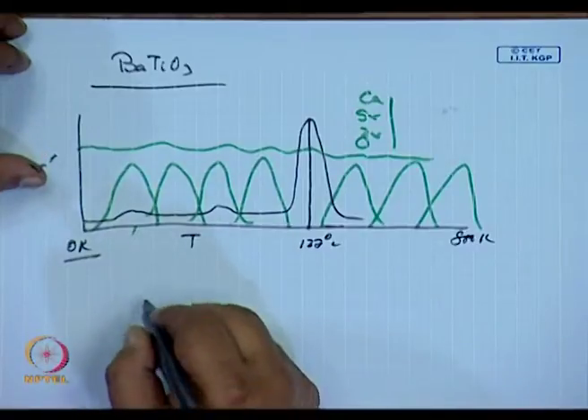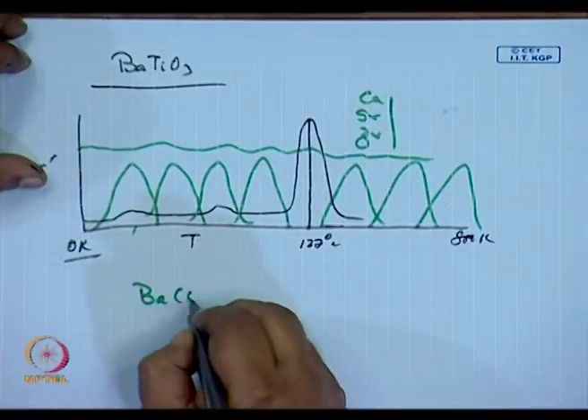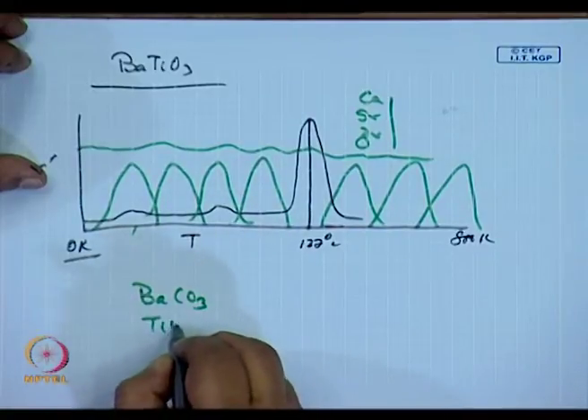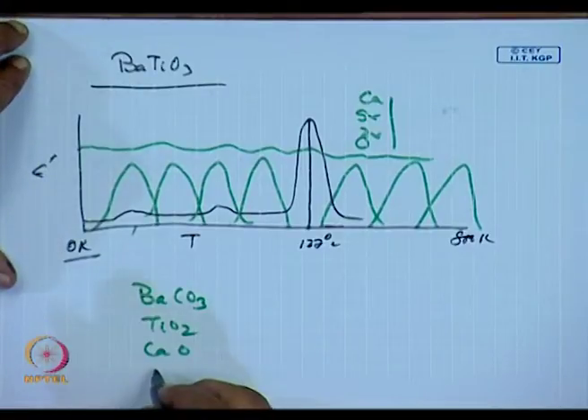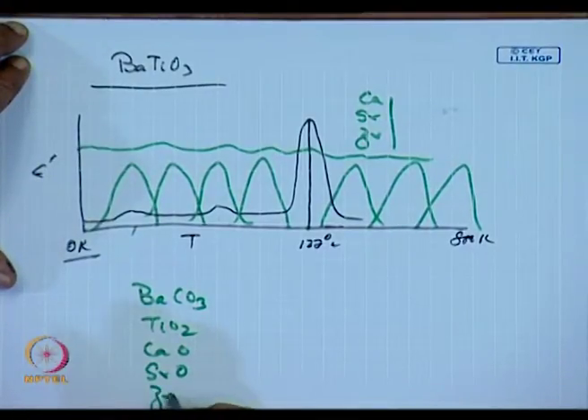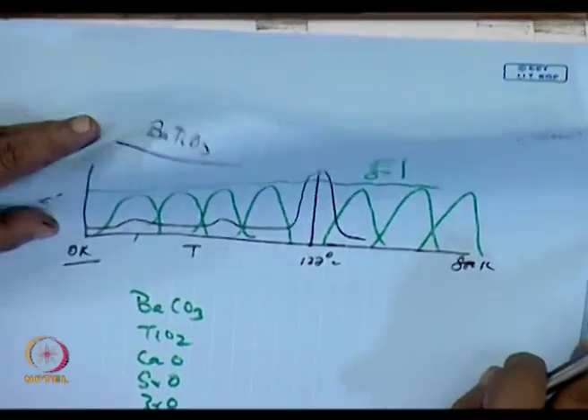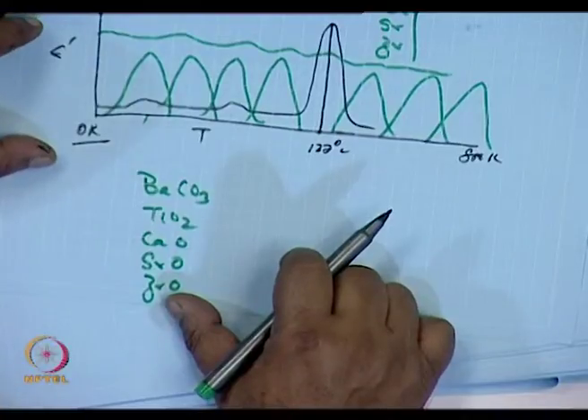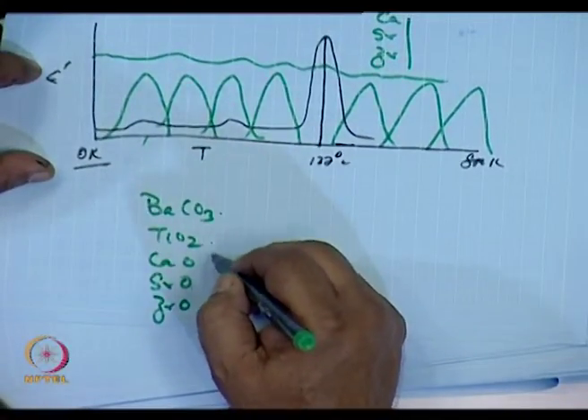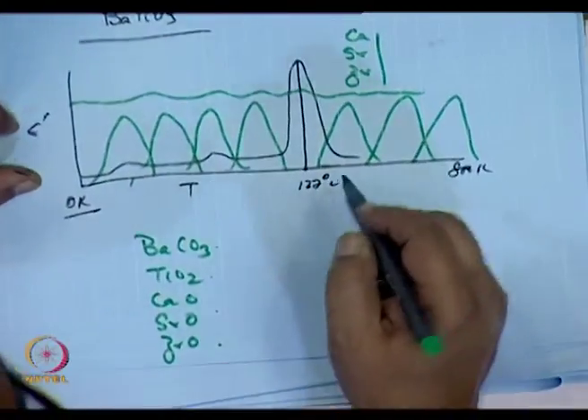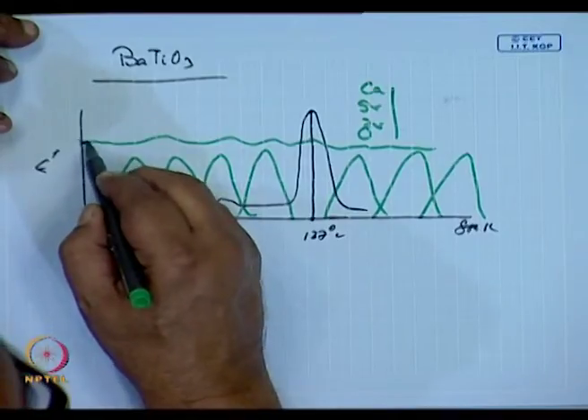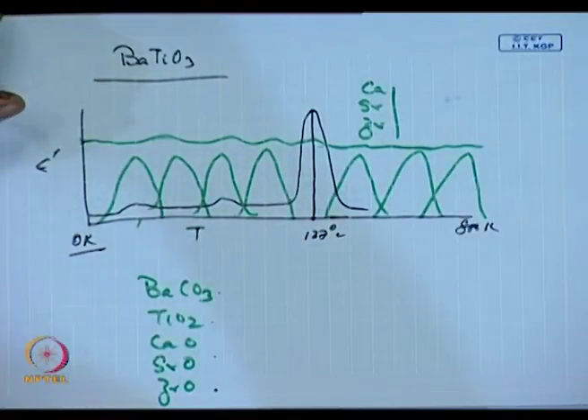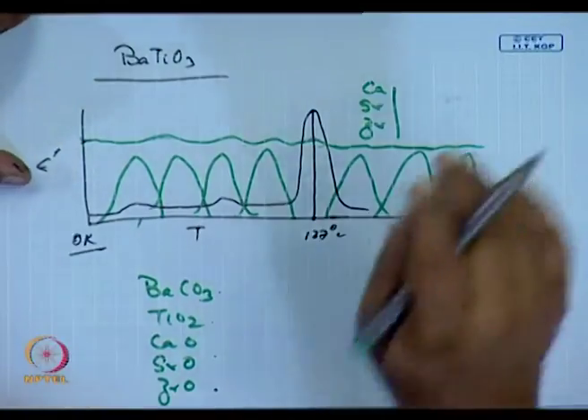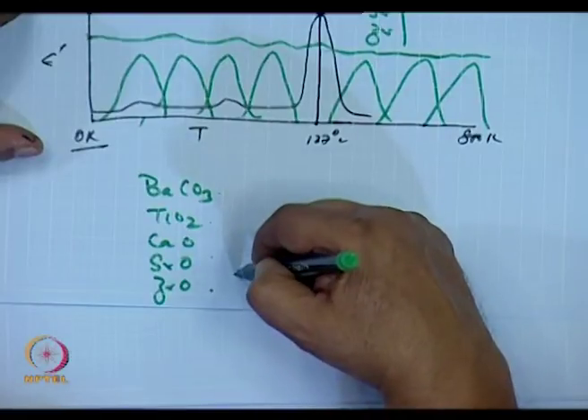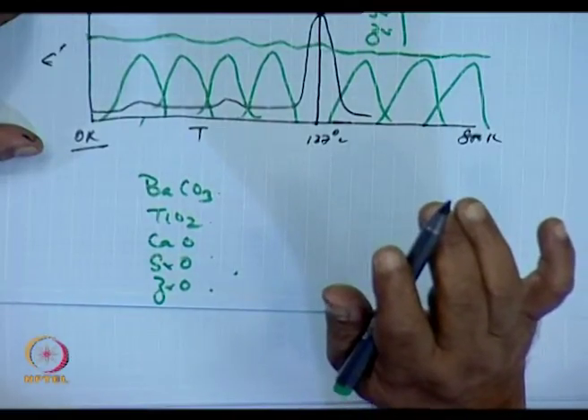So, here we will have to mix barium carbonate, titanium dioxide, calcium oxide, strontium oxide, zirconium oxide, and the list does not end here because a lot of it is in the secret zone. So, each of these has to be mixed in the desired ratio, so that the final product can give us a capacitor which has got a reasonably linear response, so that it is usable in space. Presence of impurities in this system will simply destroy the capacitance effect. So, here we need ultra pure products.